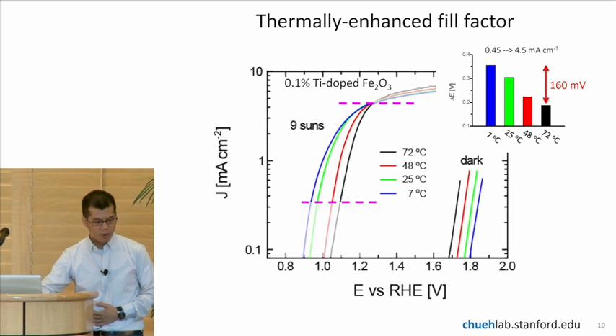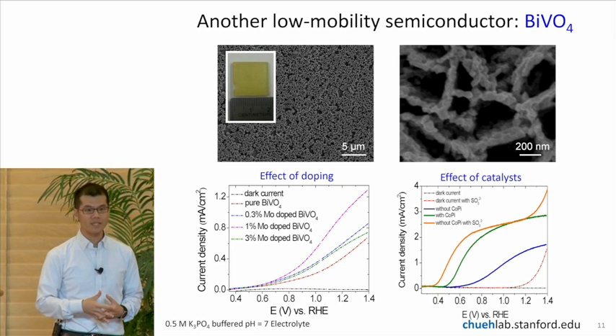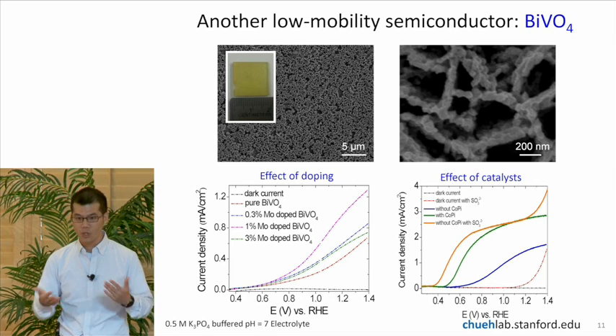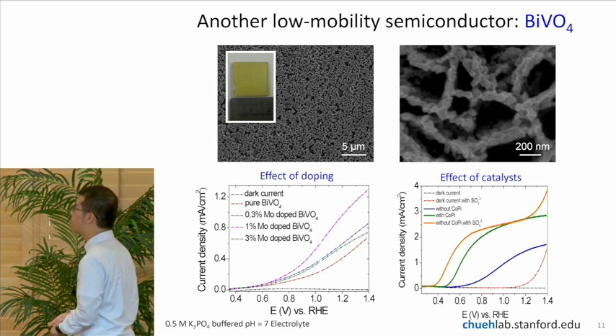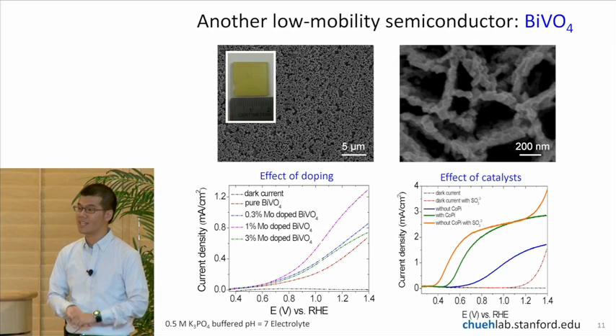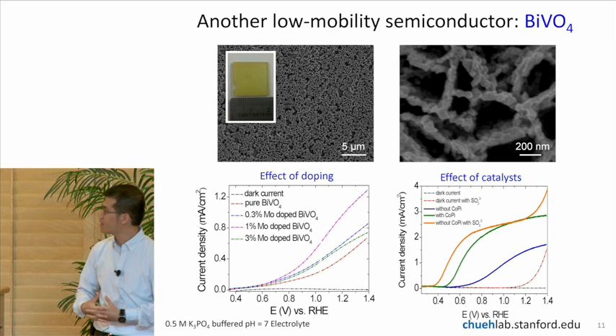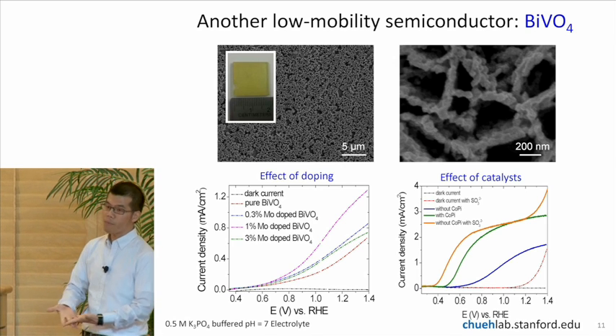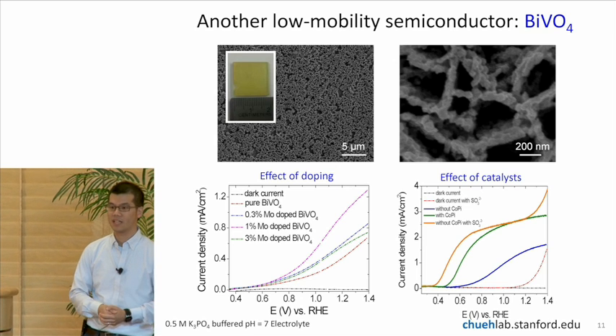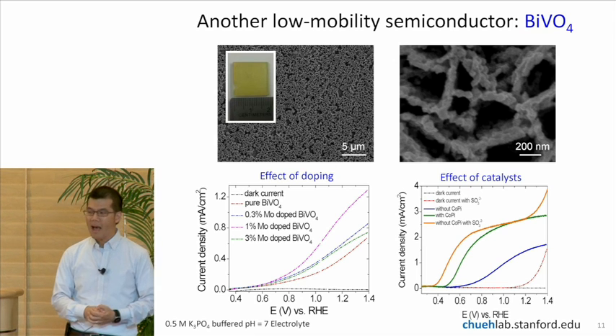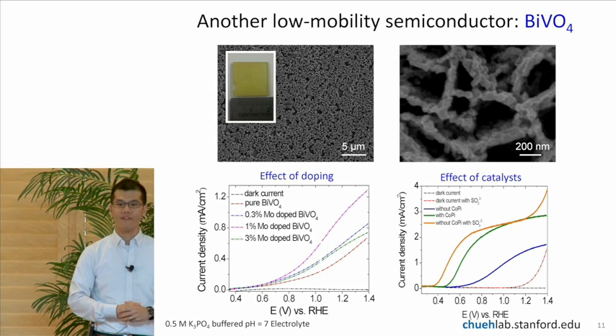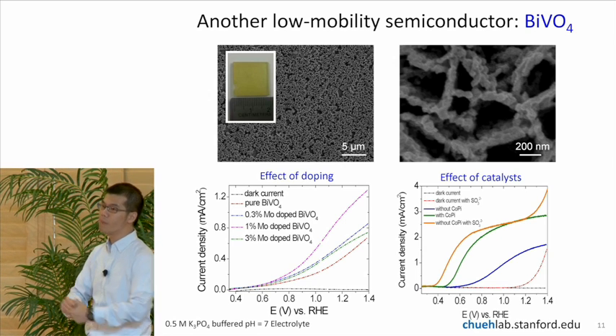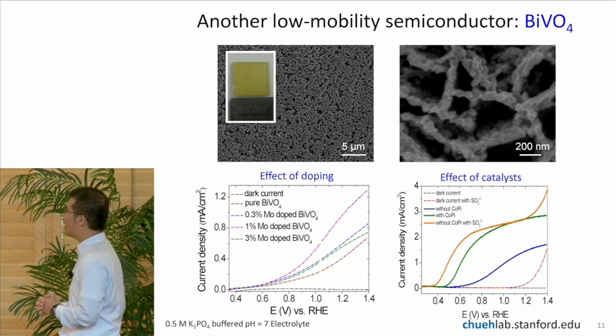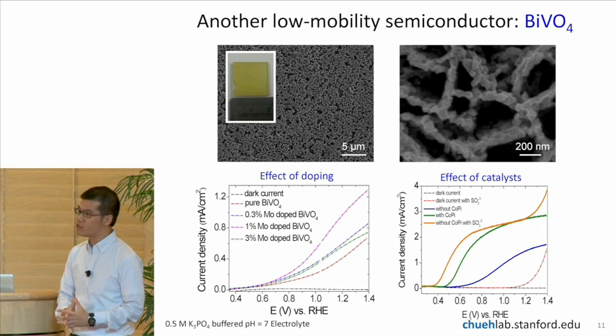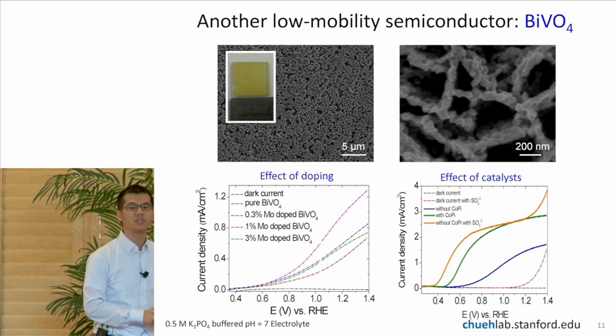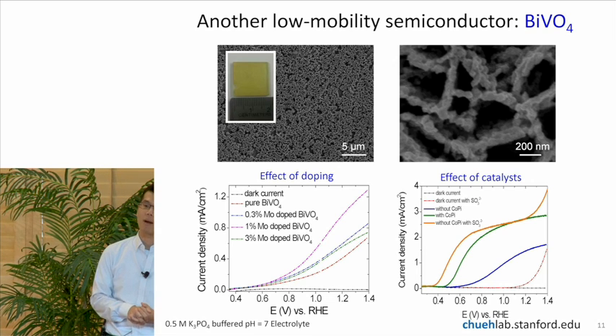So that's the first material we looked at. The second material we looked at, which also turns out to be one of these low mobility semiconductors, is bismuth vanadate. This is a material that's heavily investigated in GCEP programs and elsewhere, and it's a very promising material because it exhibits a very significant photovoltage. But one of the not so well-known facts about this material is that the electron mobility is also poor. And by increasing the thermal energy into the system, we have the opportunity to also improve its photochemical properties for converting sunlight into fuel.